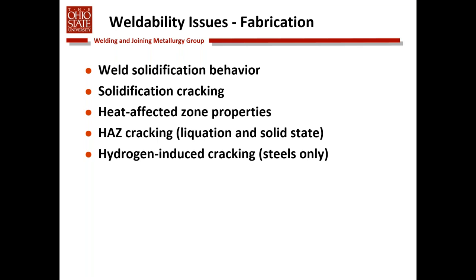Many materials, including aluminum alloys, some nickel-based alloys, some of the stainless steels, are susceptible to what we call solidification cracking. That is, they crack during or at the end of the solidification process. And there are a number of tests that have been developed to address solidification cracking.